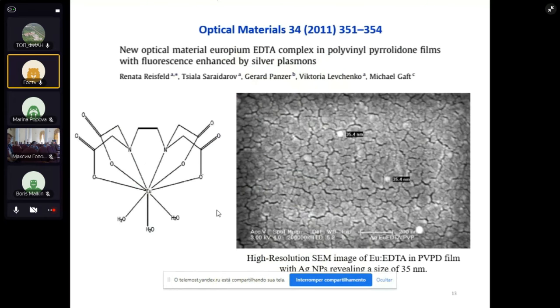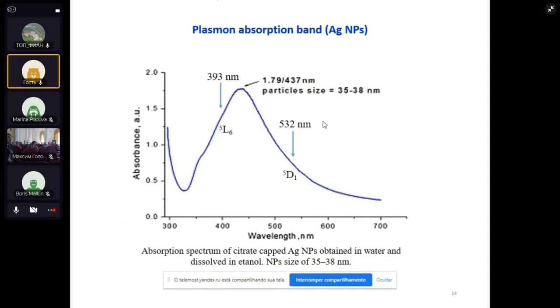And this indeed was done in a very nice experiment by the group of Professor Renata Reisfeld. They prepared a thin polymeric film and put in it a complex of europium using the EDTA ligand, precisely because the excited energy levels, singlets and triplets, of the EDTA lie considerably above the plasmon band, and they synthesized the system containing silver nanoparticles. And what they see in this case, they firstly identified the plasmon band. It's here.